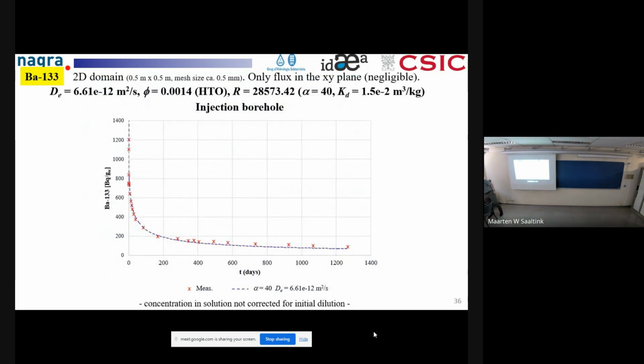And this is finally barium, more or less the same as cesium, but it's even more strongly sorbing. So the KD is something like 1.5 times 10 to the minus 2 cubic meters per kilogram. And we get the same diffusion coefficient as for cesium, so they're compatible. You see the strong drop in concentration given by this strong sorption in the rock.